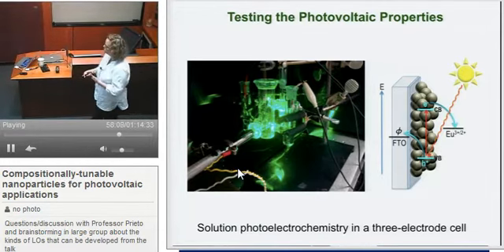So in solution, we have europium 3+ salt. We'll start with europium nitrate. The idea here is that I can collect the holes and measure that as current. The electrons are going to reduce europium 3+ to europium 2+, and then that redox couple is going to be regenerated at my counter electrode.